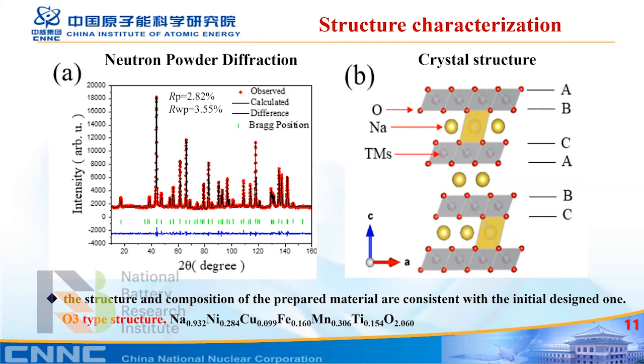We carried out our neutron powder diffraction to study the structure and composition of our samples. The structure is determined to be an O3 type oxide without any impurity. So the sample quality is perfect, so-called octahedral 3. And the refined composition is also single phase. It's consistent with our design. So that's a perfect matching.